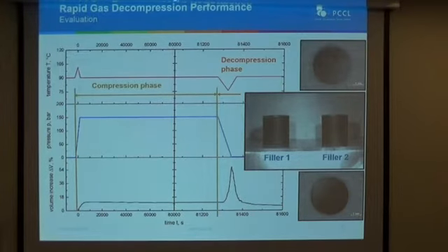Yes. So in the first cycle, the compression cycle, you see nearly nothing because it's a very, very short volume increase. We have two specimens here. Now we have the depressurization. We have only changed the filler of the material. All other things are the same. And what we see here is that we now have the volume increase.